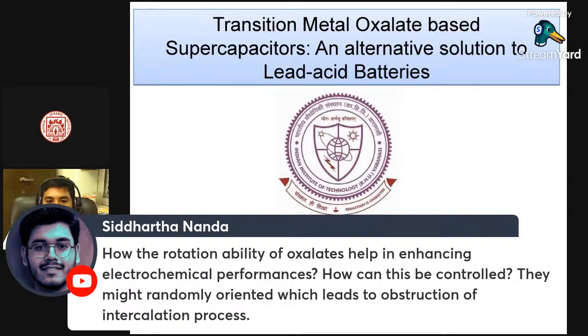So how about the rotation ability of oxalate? Okay. So see, the rotation ability of oxalate helps in getting the three-dimensional structure. See, if oxalate remains planar, then you will get only a two-dimensional structure or 2D intercalation. But if it's really a three-dimensional structure, then diffusion can be much faster. So we don't have very concrete proof currently for this rotation or the three-dimensional network. But what we are getting is a very high diffusion.